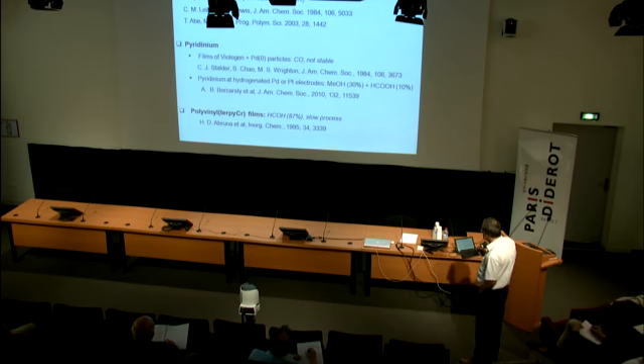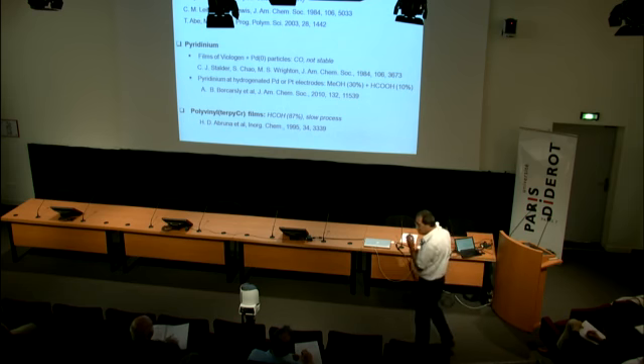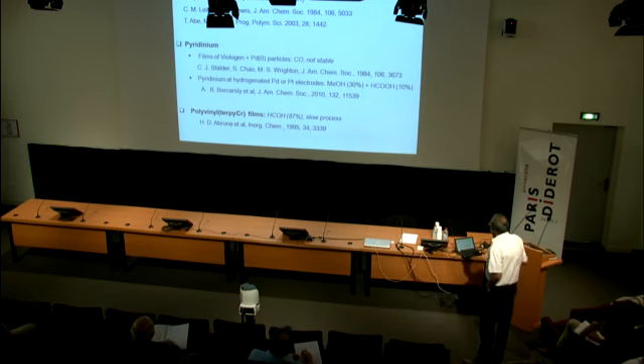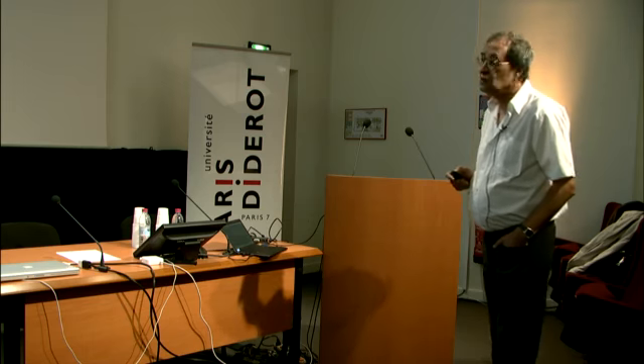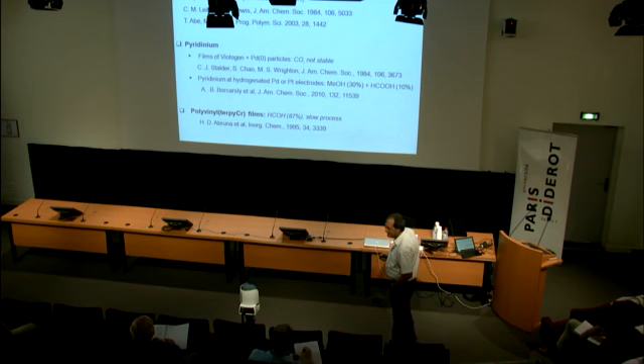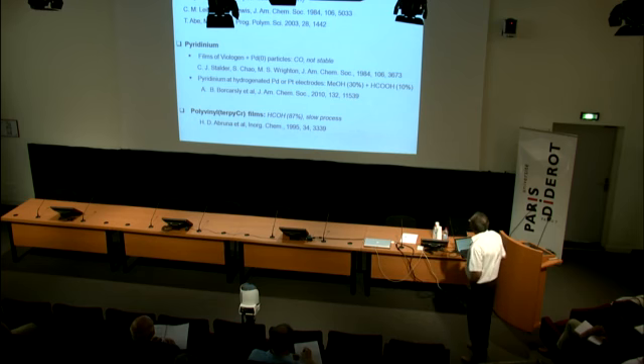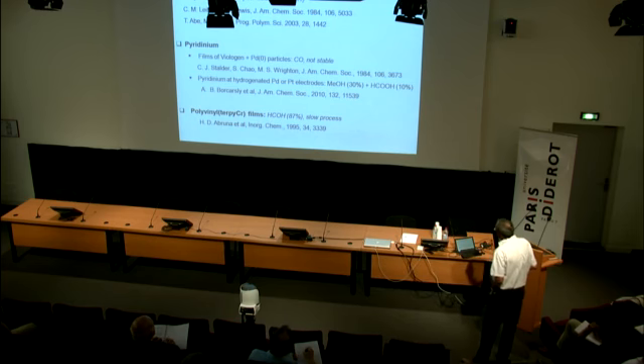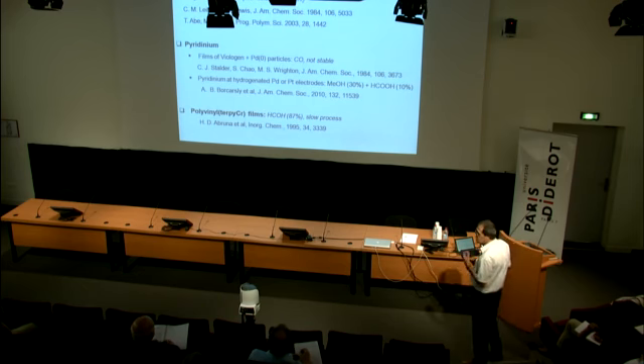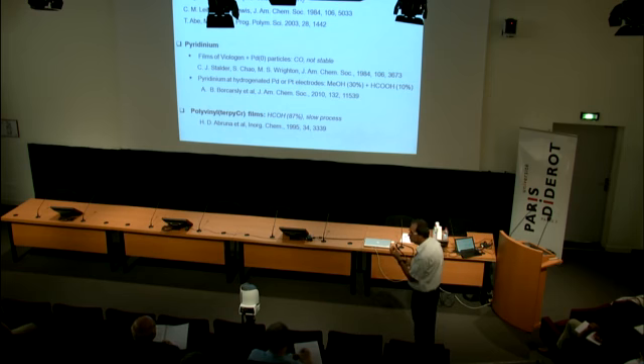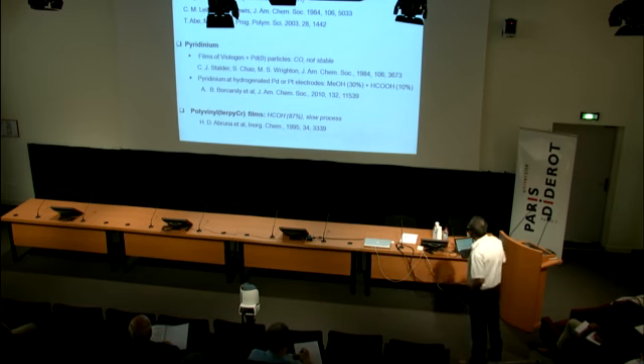It's not metallic complexes, of course. And one important work was made by Wrighton. It was a film of viologen incorporating palladium particles. They were not nanoparticles at that time. They didn't use the word nanoparticle, but probably it should be. He got nice production of CO, but the electrode is not stable. Why? Because some aggregation occurs during the process, and the activity is limited.